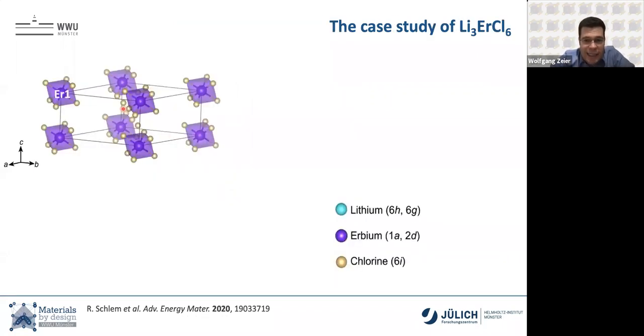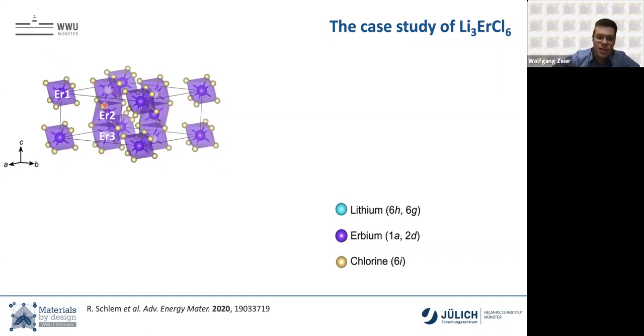The structure has, in the end, an erbium position that sits on the corner of the unit cell. You can have an additional erbium 2 position sort of in the middle, like 2 positions in the cell itself, and you can have a third erbium position that makes these virtual chains along the Z direction. They're not going to be occupied all at the same time, because if erbium 3+ is right next to an erbium 3+, that's just Coulomb-wise not gonna work. But in principle, there are these 3 positions.